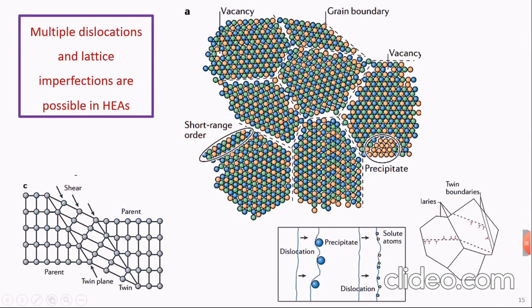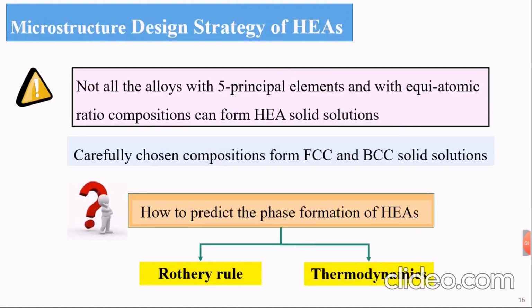And because of this lattice distortion, we have many dislocations. We have all types of dislocations you can expect in high entropy alloys. We have dislocation interactions, and all these dislocations and their interactions are responsible for the strength in high entropy alloys. So this lattice distortion effect is very important.